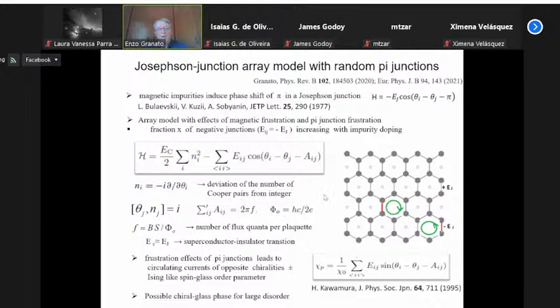And the fact that the coupling can be negative leads to frustration effects, even at zero field. Even though there's no magnetic field here, you still have frustration, because the number of negative junctions in a plaquette is an odd number. So this can give rise to a circulating current in the plaquette, even though there's no external field. And since the negative junctions can be in different positions, these current loops can be in different phases. So there's a kind of glass. So the frustration effect of pi junctions located randomly leads to circulating currents of opposite polarity, which act like Ising spins or a spin glass, or the chirality.